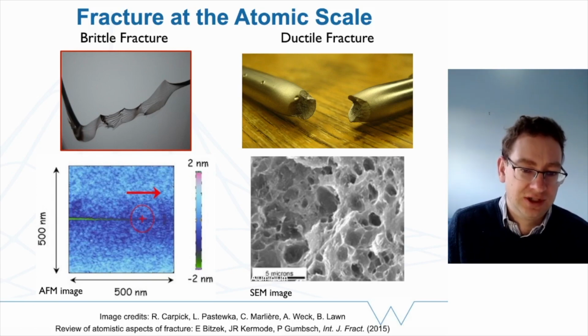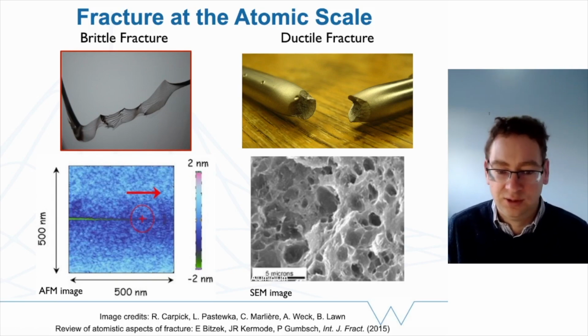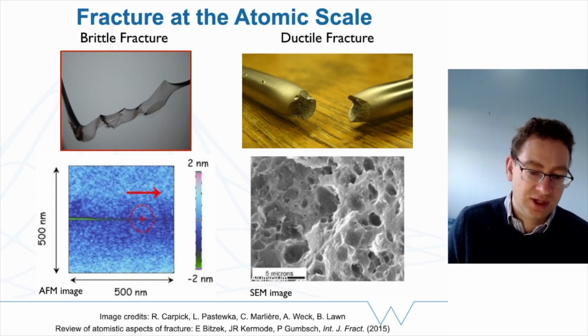If you zoom in on what's going on inside a ductile fracture, you find it's quite different to the very sharp brittle case that we see in glass. Instead, there are lots of little holes called voids that grow inside the material, and eventually enough of those holes combine and make a critical size void, which causes the material to fail. So it's quite a different process.